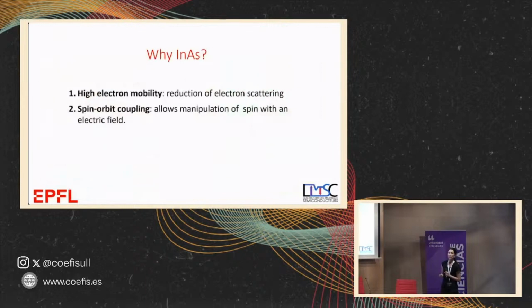So why indium arsenide? First, because it has very high electron mobility, and electron mobility means that if you look at electrons in a metal, and you put a voltage, they will go from one side to the other, but in between, they will hit each other very often. And if you do this, then they lose coherence. And what we want is that the electrons stay coherent as long as possible. So you want to avoid these collisions, and one measure for this is the mobility. This characterizes how many collisions will happen.